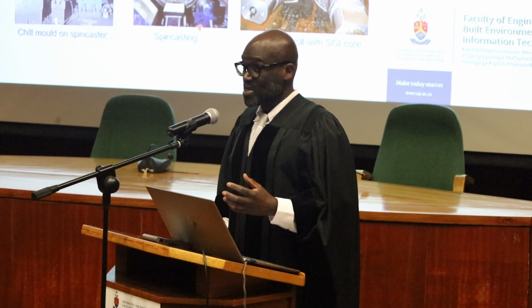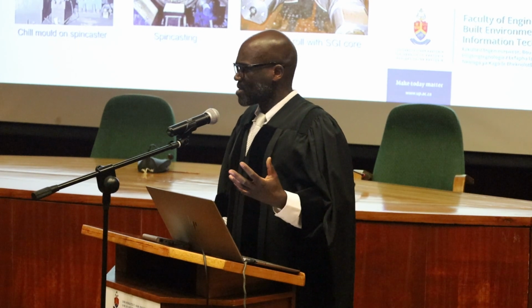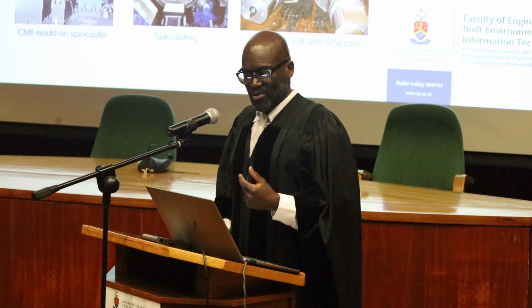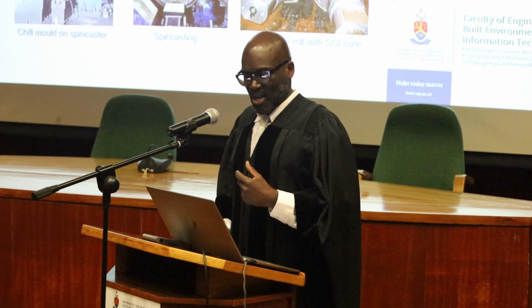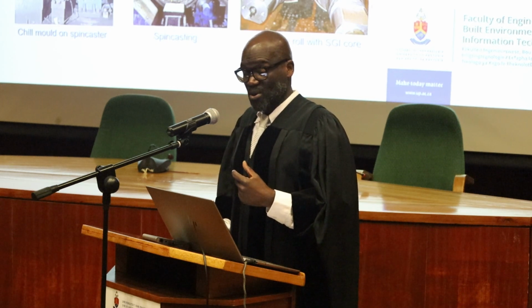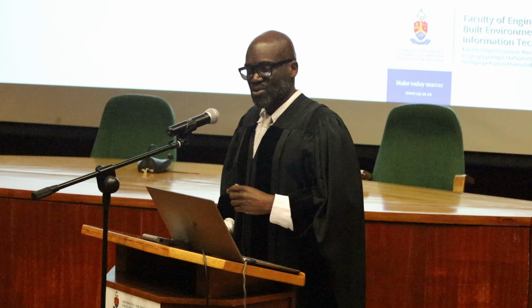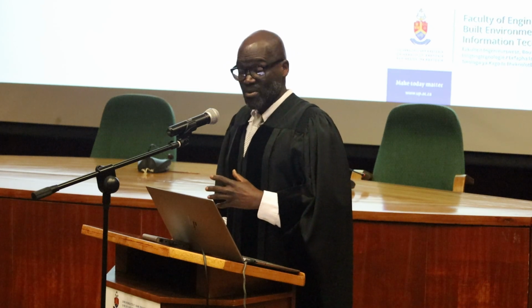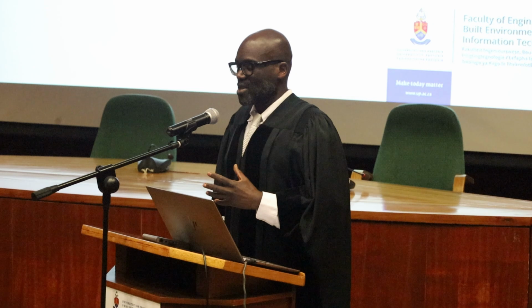So the spin caster was set, and spin casting was done. Spin casting is the same as centrifugal casting. When the shell was cast, this unit is flipped into vertical position, and the spheroidal graphitic iron core is cast inside there, and thereafter you do the machining of the final roll. So this is what you see. What was done next was to use this huge iron ball to smash these shells so that we could get some samples, and sampling was done.